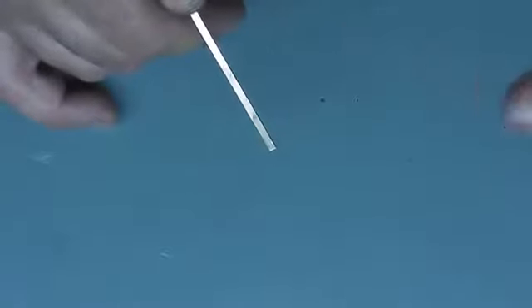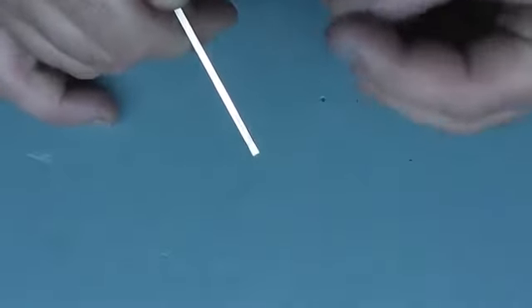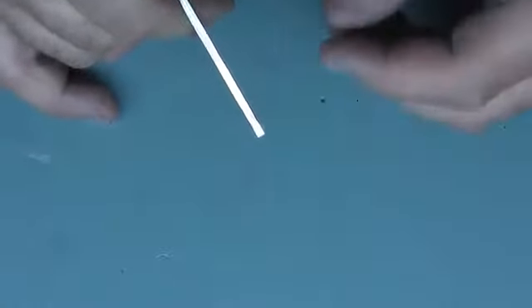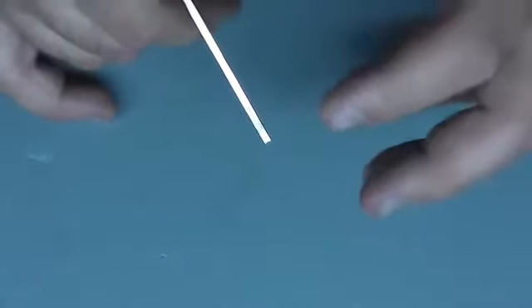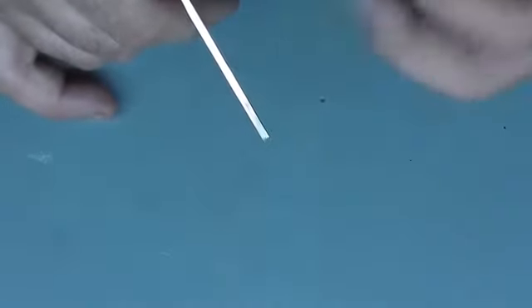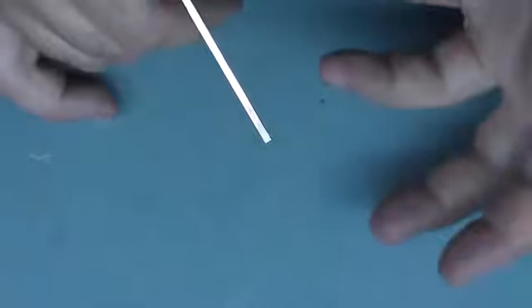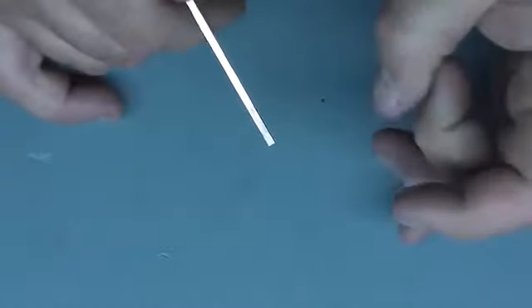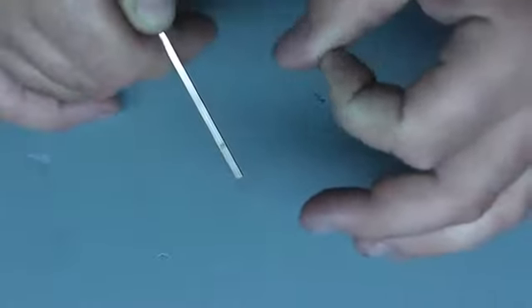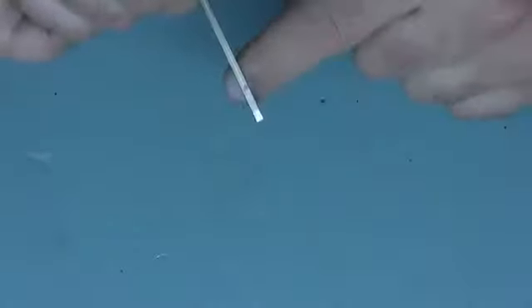Now, where are you going to find gaps in pipe? Well, I've noticed that sometimes you get really crappy fittings and loose fittings, and usually that's on the back of an evaporator coil where the suction and liquid line comes in. Like if you're replacing a coil, for some reason those swedge joints are just slightly too big, and the pipe likes to float in it. So what I like to do is braze that one joint and soft solder the rest.